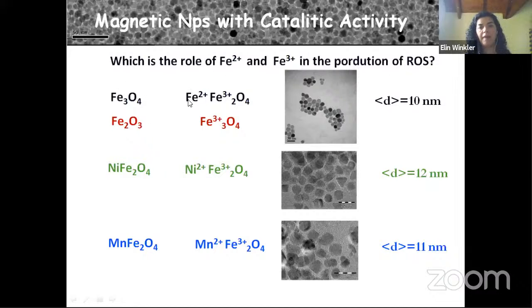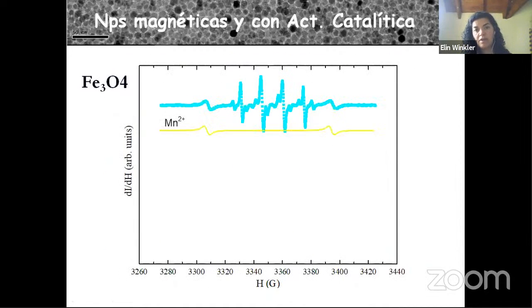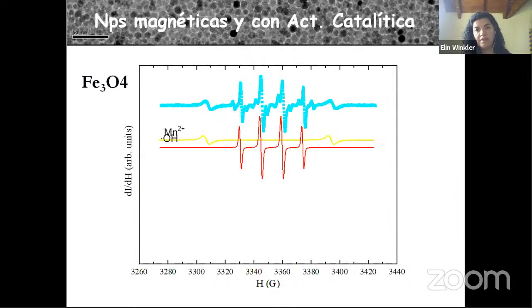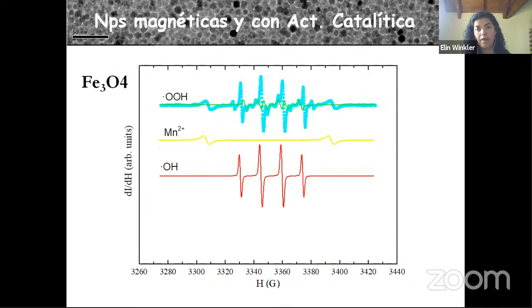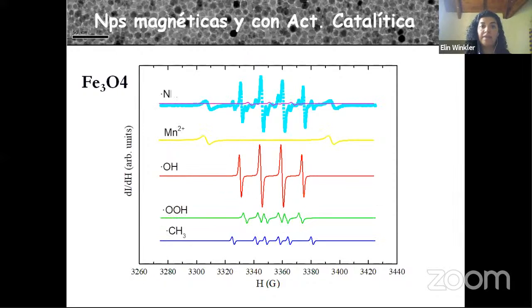This system has 1/3 of iron 2+. When oxidized, this nanoparticle has only iron 3+ in the system, and then we have nickel 2+ and manganese 2+ with all iron 3+. And we fit the spectra. In that way, we can identify all the radicals that we have, and we can quantify them in each case.